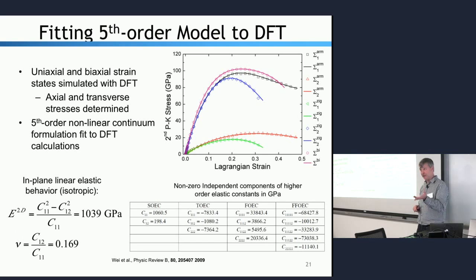But if you look at the energy, I think Boris has some numbers. I've used your papers for looking at the bending energy of a graphene sheet. And if you plug that energy in, how much energy does it take to just bend the graphene around the tip compared to the strain energy? It's tiny in these experiments.